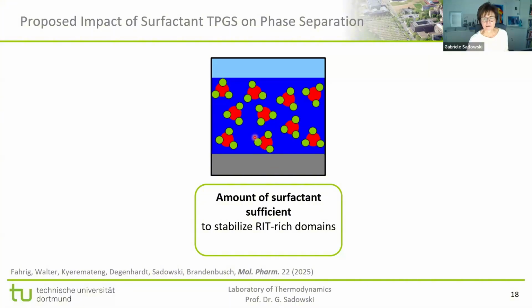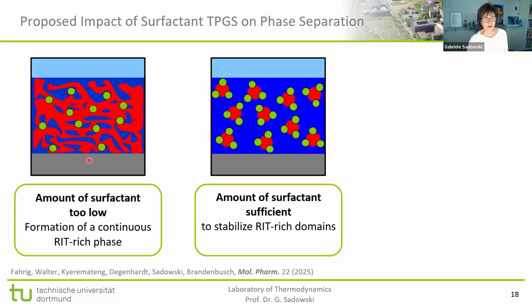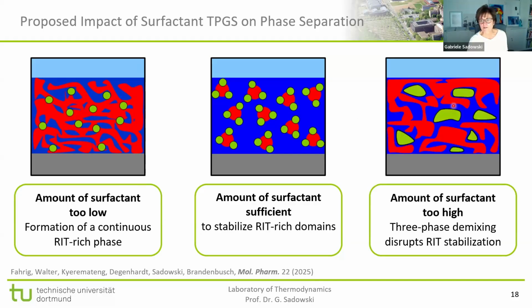So this is what we say. A certain amount of surfactant is fine. It stabilizes the ritonavir-rich domains. If the amount is too low, it cannot prevent forming the two phases and this morphology, and we will not have nice dissolution of the ritonavir. And if the amount is too high, we have three phases, and this is then still not what we want to have, because we will have no release of ritonavir, of the API, or at least only very low release in this case. So there is a certain window of surfactant compositions that do the job.